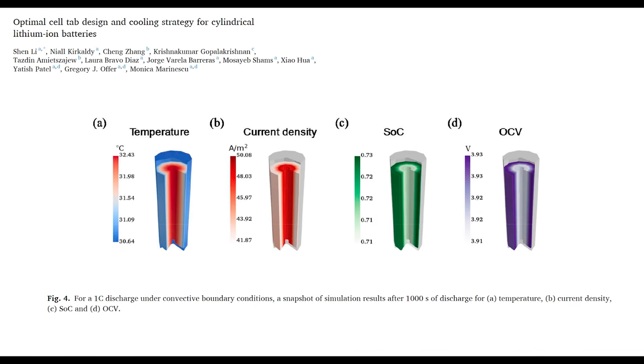The weakest link effect doesn't just occur between battery cells, but also plays out within battery cells. This is because thermal gradients form within battery cells as they charge and discharge. As this image shows, the core of a battery cell traps heat while the surface remains comparatively cool. The local fluctuations, over time, lead to some areas of the battery cell degrading more quickly than others. The areas that are degraded become the weakest link. To further complicate things, the local fluctuations and degradation can be exacerbated by the quality and consistency of the materials used in the battery cell, as well as the design of the battery cell.